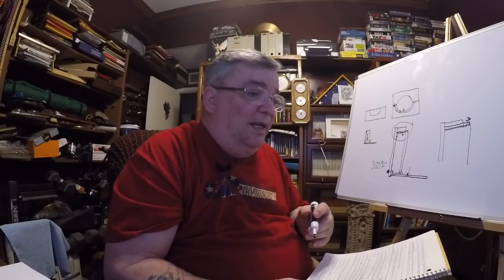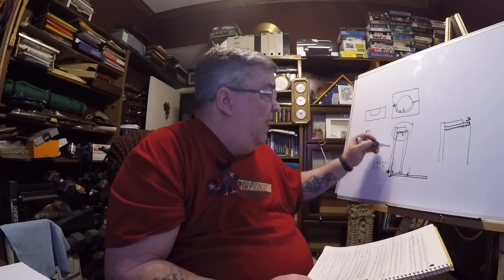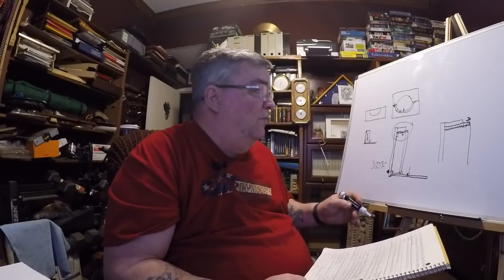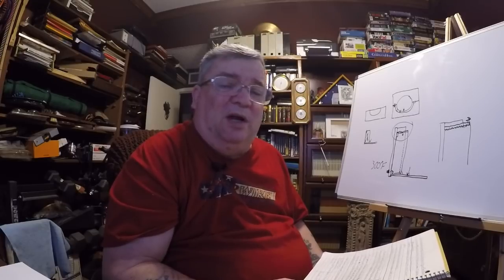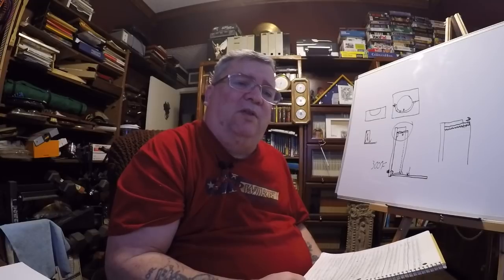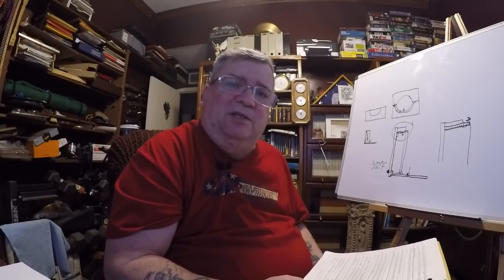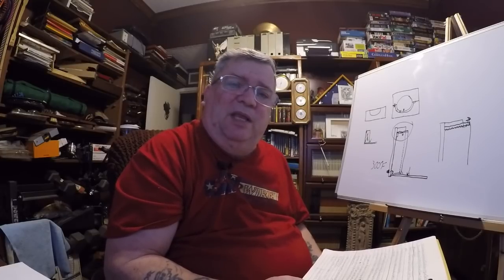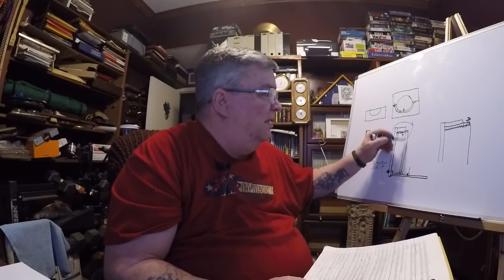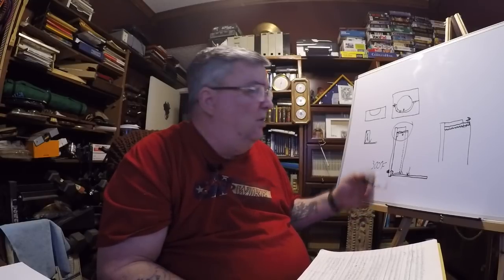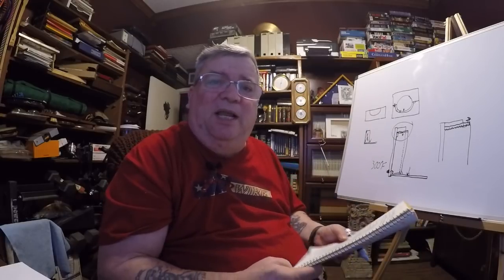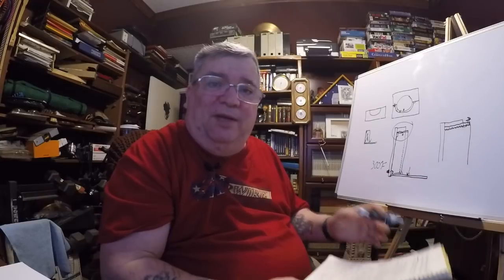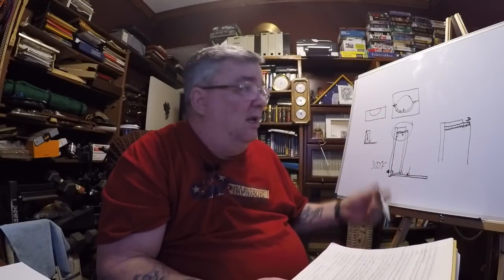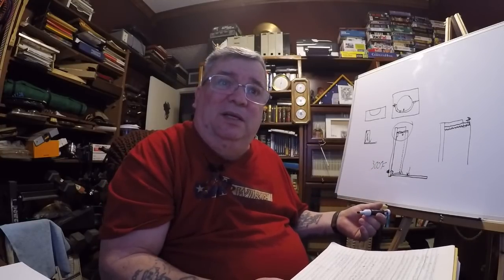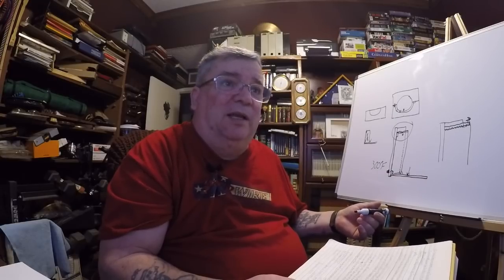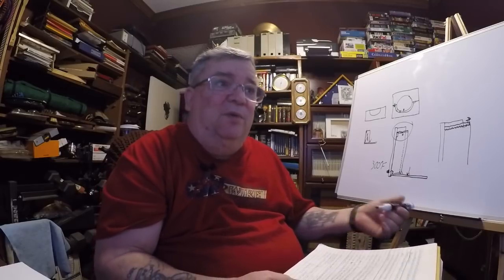What we used to do, and I know we were wrong doing it, we would bring the temperature of the mandrel and all that up to the melting temperature of tin. I noticed in those times that with all this work that we've done to get rid of all the oxides and such, it sure does seem that we're making a lot of oxide by bringing the tin up to molten temperature, because it's not even paper thin. It's very thin, and you have just a small amount of mass in there being hit by a lot of heat. That accelerates the growth of oxides. I saw that the tin was turning not silver anymore, but a dark color, almost like lead. So it was forming the oxides.